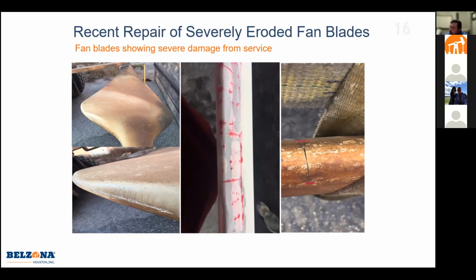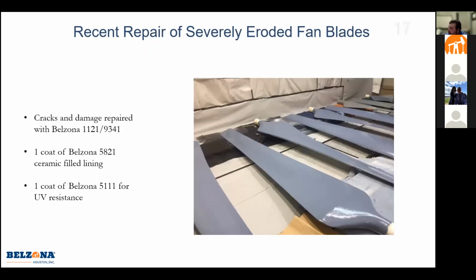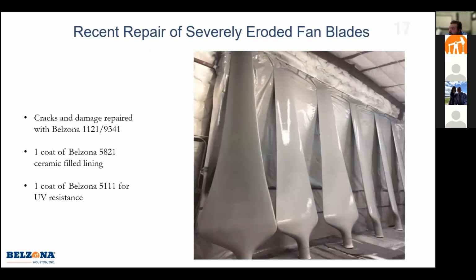So we went in, we used our paste grades and our resins to repair these cracks, especially the ones on the leading edge. And we gave it one coat of our ceramic filled lining to the entire blade. That's what you can see here. And then for a final top coat, we gave it our UV resistant coating to help it from UV attack while it's spinning in the sun.